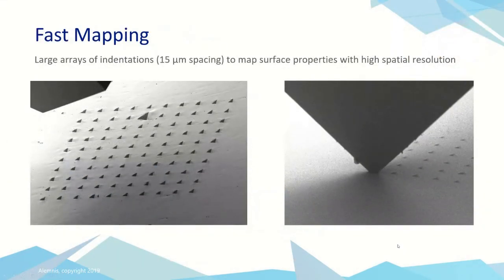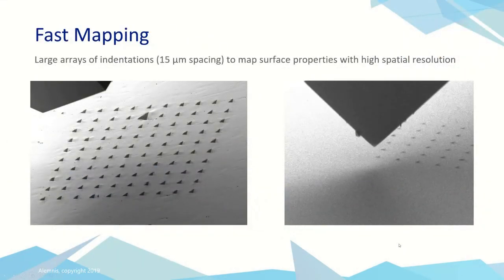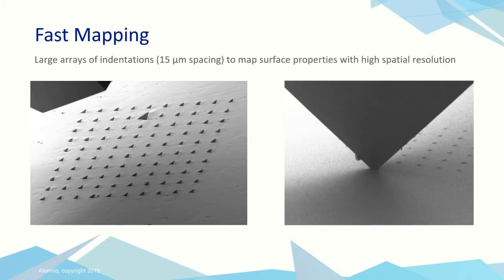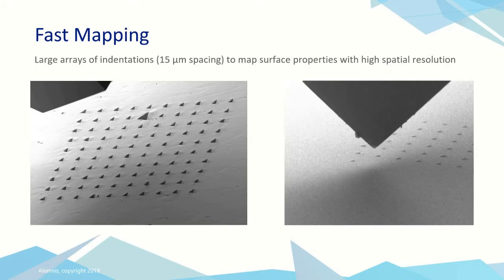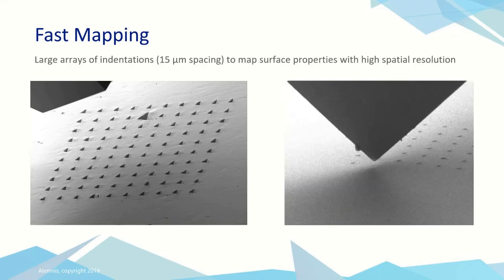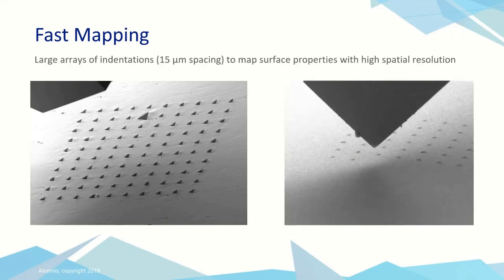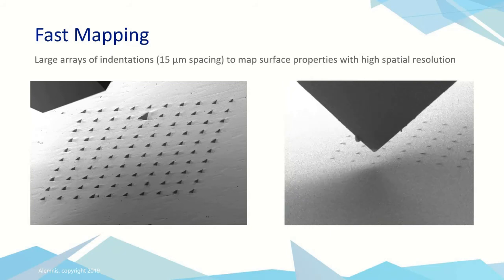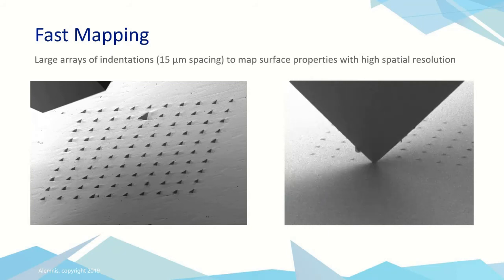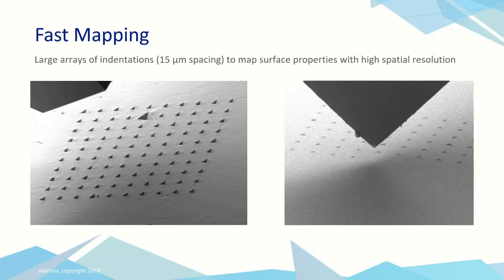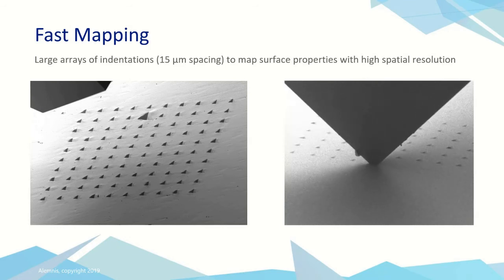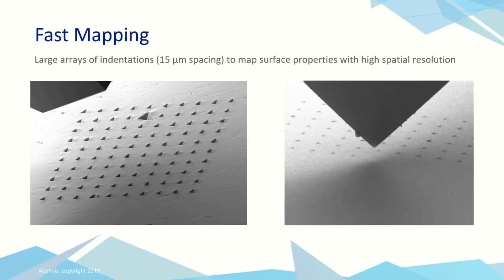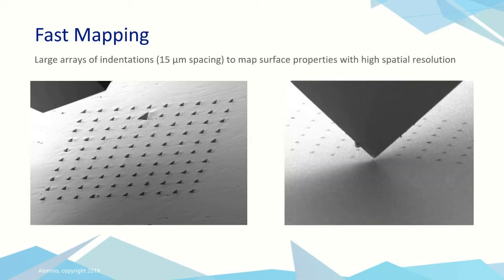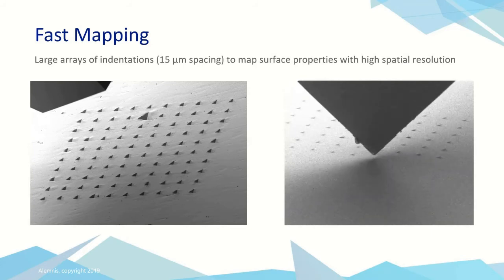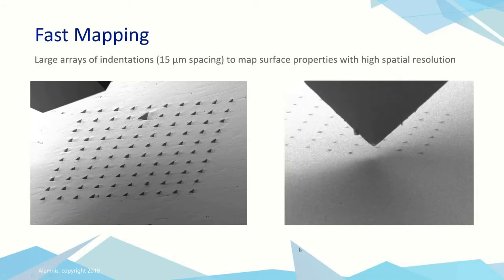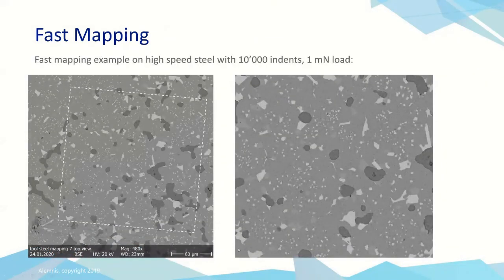And just to finish with, I wanted to come back to the fast mapping solution, because that's really the direction in which nanoindentation is going, to be able to map arrays of indents across a surface. And if you can combine that with AFM, it means you really have a powerful technique for understanding mechanical properties and surface properties across fairly large areas. So mapping today is done very fast, typically an indentation per second, as you can see here. And it allows us to map properties.